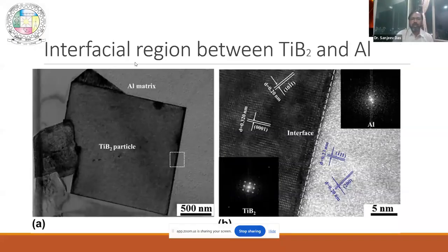Now, how does it work? Suppose TiB2 is a nanoparticle that you are putting inside the liquid metal. It will help in nucleation of a grain. These are TEM images, and you can see that aluminium is nucleating on the TiB2 surface. So if you have a lot of particles inside the liquid and solidification starts, then each TiB2 particle will start nucleating, and you will get a lot of fine grains, and these grains will stop the growth of the other grains. Like that, you get the refined structure.